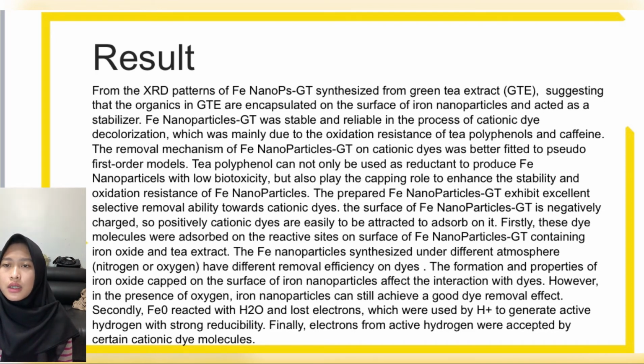Next, the result from the XRD patterns of FeNPs-GT synthesized from green tea extract GTE, suggesting that the organics in GTE are encapsulated on the surface of iron nanoparticle and acted as a stabilizer. FeNPs-GT was stable and reliable in the process of cationic dye decolorization, which was mainly due to the oxidation resistance of the polyphenol and caffeine.